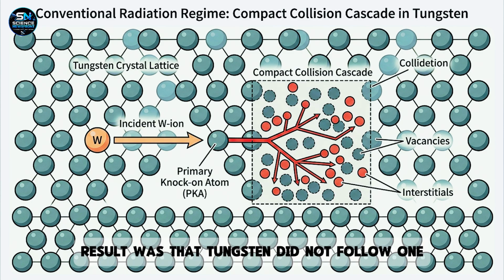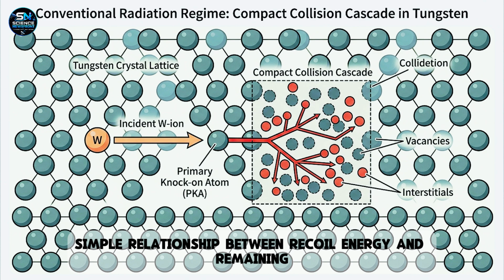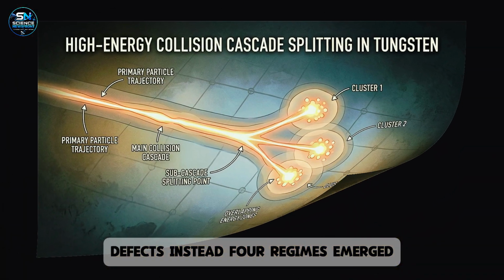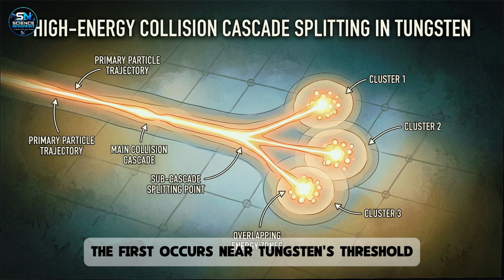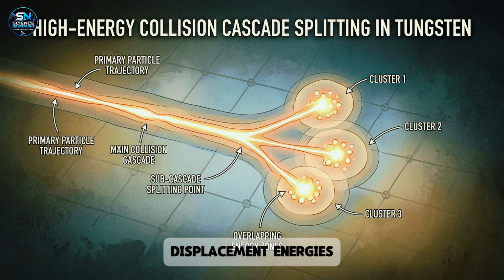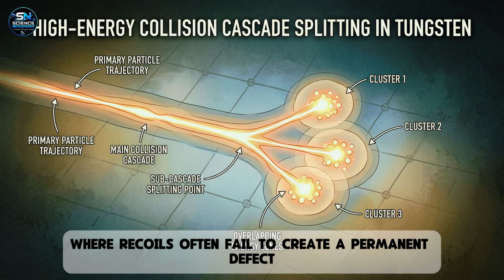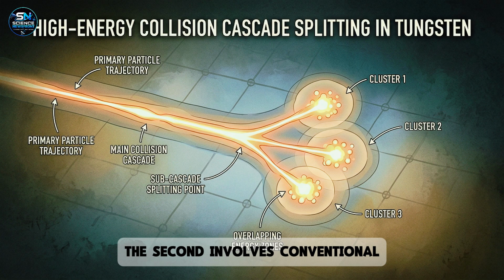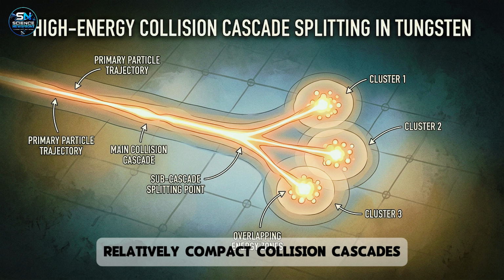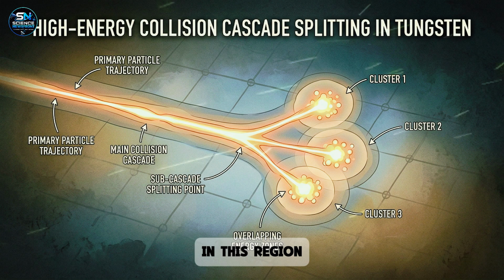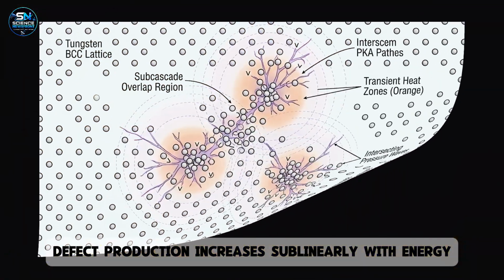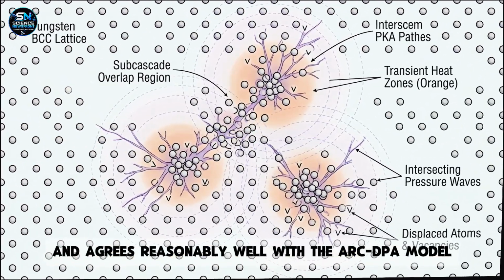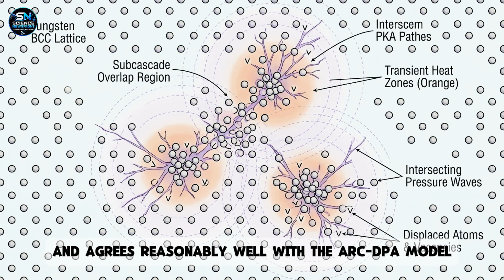4 different radiation regimes. The most important result was that tungsten did not follow one simple relationship between recoil energy and remaining defects. Instead, 4 regimes emerged. The first occurs near tungsten's threshold displacement energies, where recoils often fail to create a permanent defect. The second involves conventional, relatively compact collision cascades. In this region, defect production increases sublinearly with energy and agrees reasonably well with the ARC-DPA model.